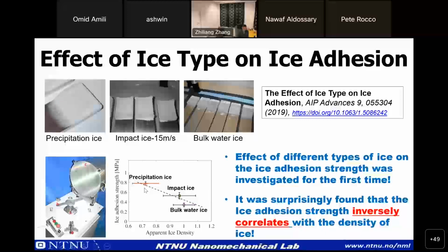What we found is that the ice adhesion strength is inversely proportional to the density of ice. This was a very surprising result. In fact, no one believed that. It was very difficult for us to publish this result. But once we published, everyone is citing our paper. So we have got a lot of citations on this paper. So ice adhesion depends also on the type of ice.